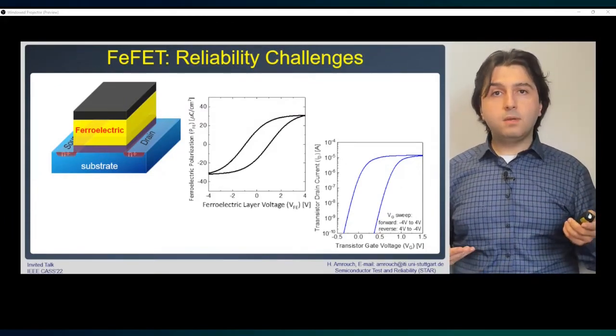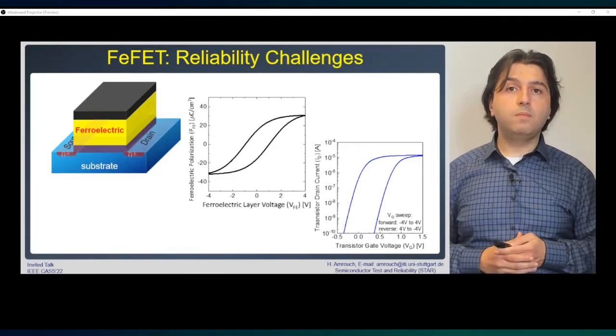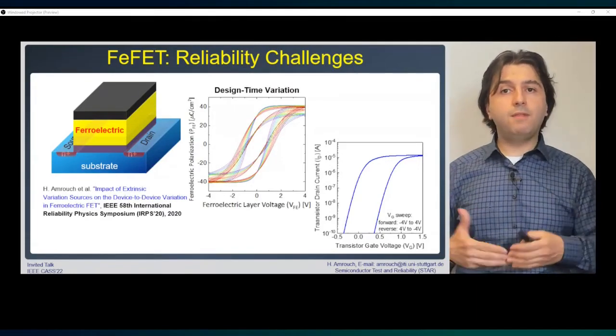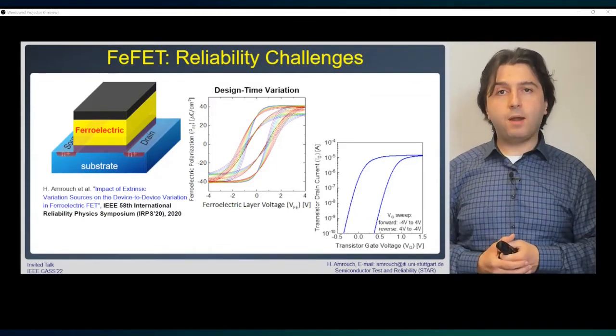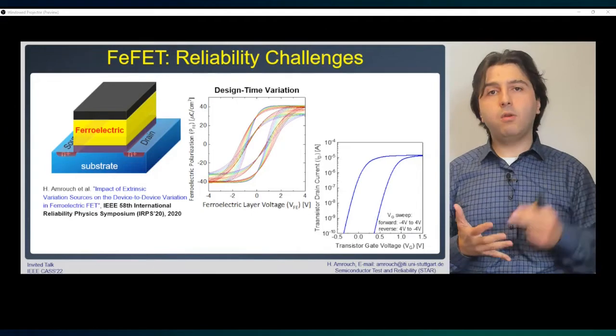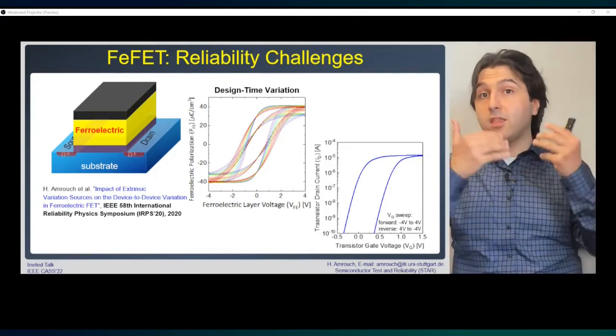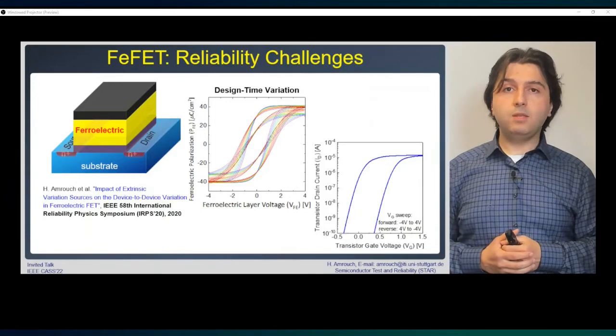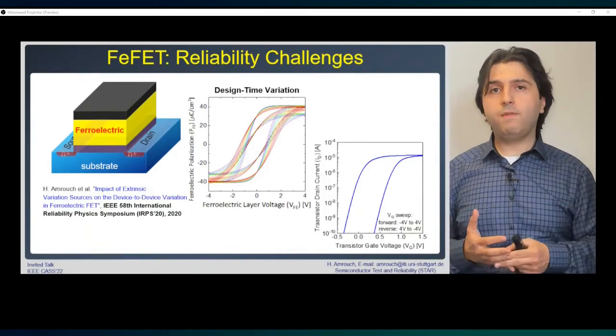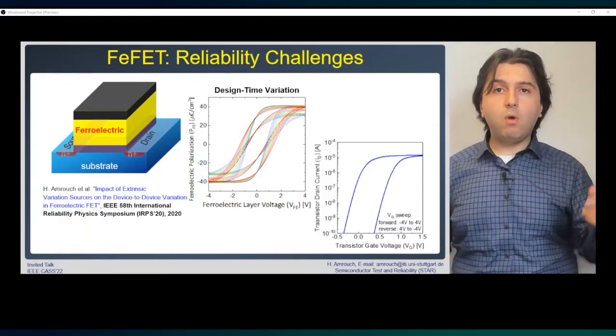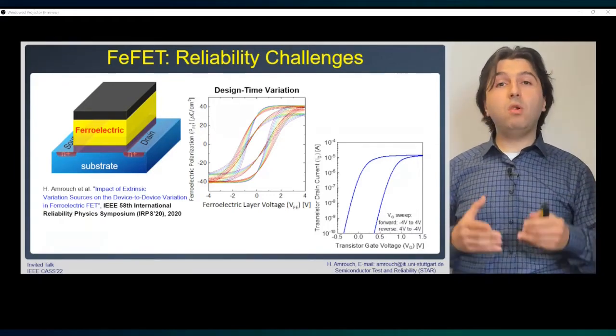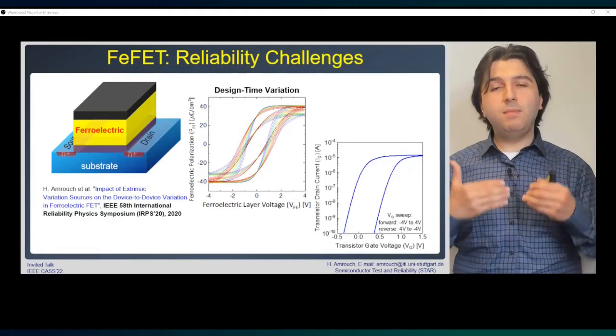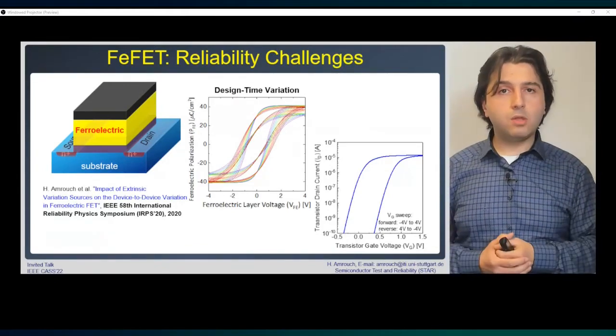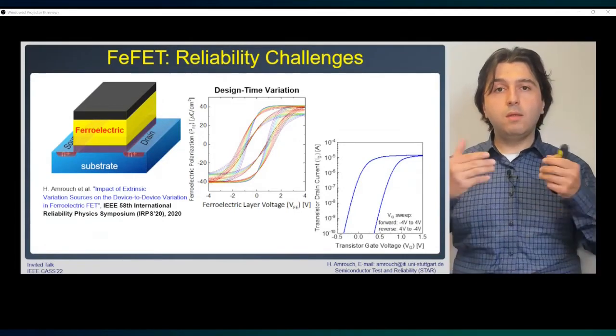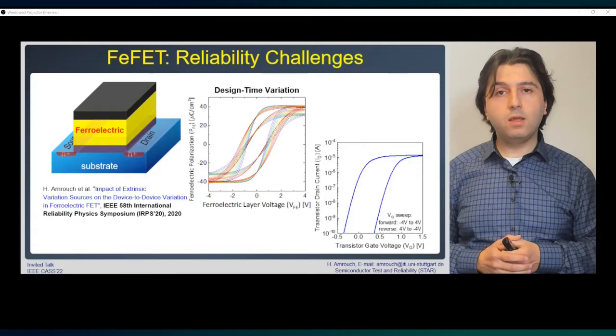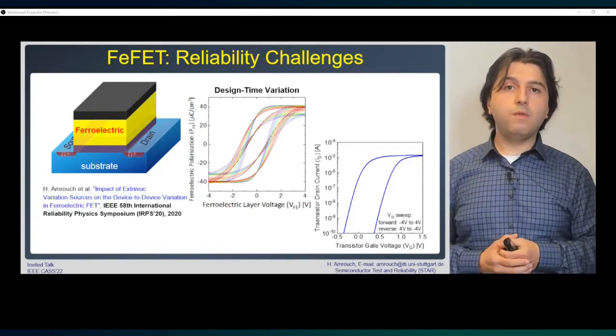The famous reliability challenges come, of course, from variability. Design time variability comes from the variation in the underlying physical parameters, such as the thickness of the ferroelectric layer, the remnant polarization, the coercive field, as well as traditional manufacturing variability sources like random doping fluctuation, surface roughness, and work function fluctuations, all variability sources that are extremely dominant in deep nanotechnologies. Together with the additional variability coming from the ferroelectricity, of course, we get lots of problems in the design time.